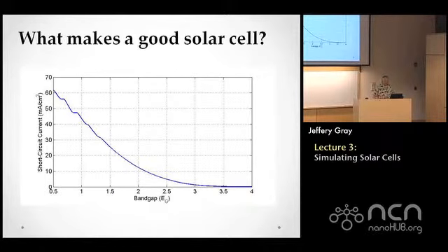Now, I guess I'm going to use this right here. But you can see that, let's say I use silicon, I'm only going to use this part of the spectrum. And these higher energy photons I'm probably not using very effectively. Suppose I have a 2 eV photon, I'm using less than half the energy of that photon in the device. So coming up in the talk, we're going to talk about multi-junction PV systems.